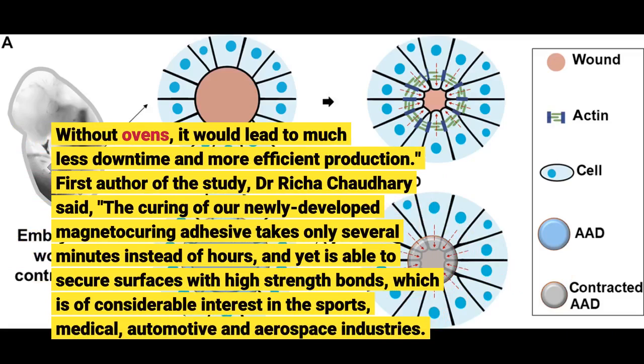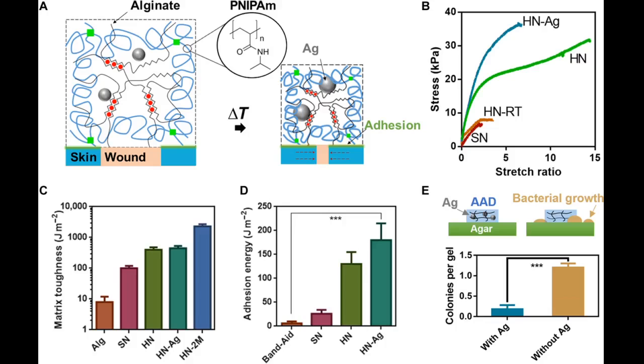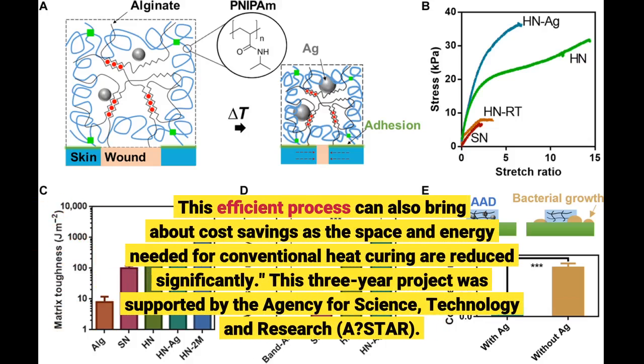First author of the study, Dr. Richa Chaudhary said, "The curing of our newly developed magnetocuring adhesive takes only several minutes instead of hours, and yet is able to secure surfaces with high-strength bonds." This efficient process can also bring about cost savings as the space and energy needed for conventional heat curing are reduced significantly. This 3-year project was supported by the Agency for Science, Technology and Research, A*STAR.